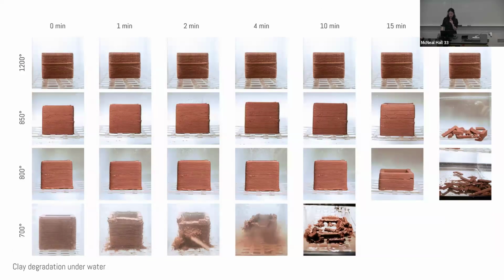So we conducted a series of experiments to evaluate the durability and permeability of prototypes under controlled aquatic conditions. The first test submerged simple prototypes fired at sub-vitrification temperatures ranging from 700 to 1200. You can see the bottommost is 700 and the topmost row is 1200 degrees. We used the results to narrow in on a range of potential firing temperatures. As you can see, many prototypes disintegrated, especially the ones at the lower temperature, too quickly for it to be useful for landscape intervention, so we discarded them.